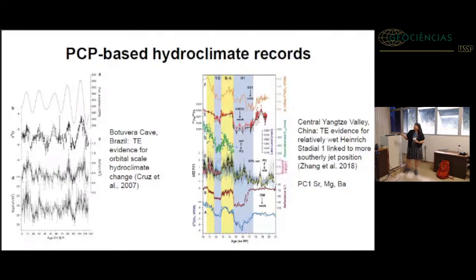And this is another example of a really interesting way that trace elements can complement our interpretations of paleoclimate by providing more specific information about local rainfall. And this is especially important, I think, in areas where the interpretation of the oxygen isotope signal is unclear, like the Asian monsoon region, we know that it's this large-scale signal that isn't necessarily directly related to rainfall amount at a specific location, but we can look at things like carbon or trace elements, which are driven primarily by local processes to distinguish that. And so this study was quite surprising in that it found that Heinrich Stadial 1, which is widely seen as this weak monsoon period in China, actually was wetter in the central Yangtze Valley region, and that was linked to changes in the seasonal transitions of the westerly jet.